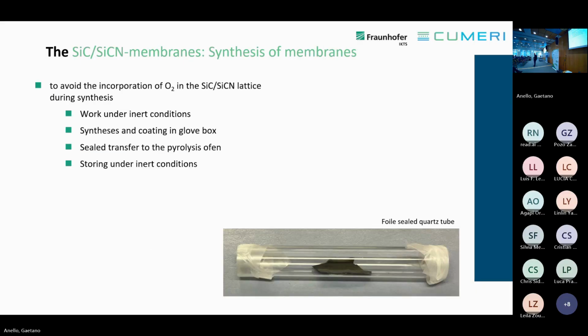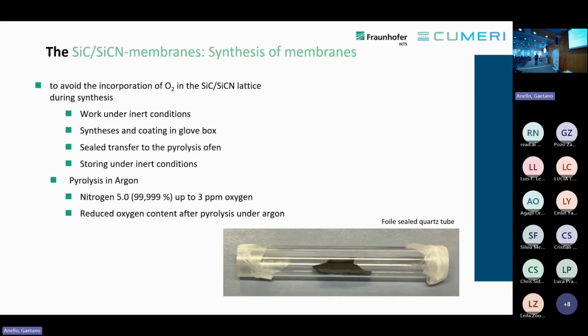However, preparation of oxygen-free membranes is challenging. You always have to run the work in inert conditions until you have a ceramic material. So we have to make the synthesis of the polymers and the coating in a glove box. We have to transfer the coated membranes into the oven in inert conditions, and also store the coated membranes in inert conditions before they are sintered. And during the pyrolysis, we found out that nitrogen 5.0 still contains some oxygen, which we didn't know before, so we had to change to argon.